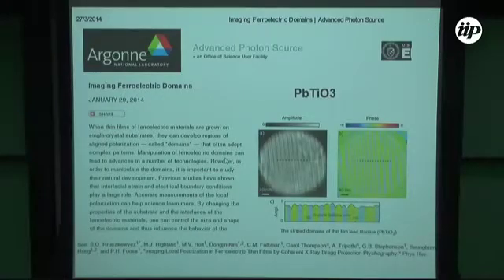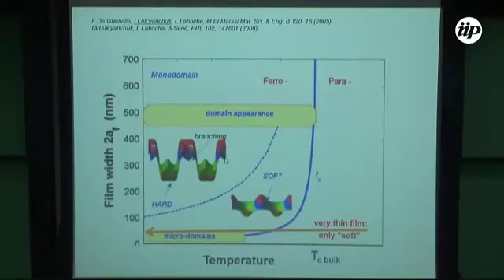Now I will show the development of the situation. So now it's possible by different, quite sophisticated synchrotron methods to visualize this lattice. So this was our prediction in 2005, the renormalization of the critical temperature. So you see it is renormalized, but not so dramatically as it would be for a monodomain sample. And another interesting observation was that, actually, we call this a soft domain. A soft domain is actually not really the domain which was assumed by Landau, Lifshitz, Kittel and company that exists in magnets.